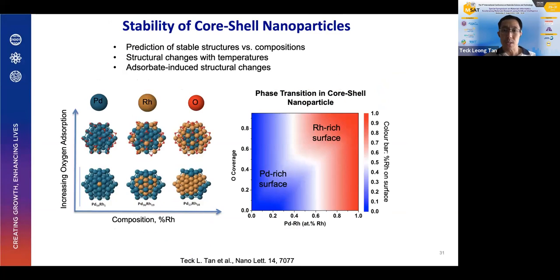This is to show that we can use similar methods to study what we call adsorbate induced phase separation. If you look at the diagram on the left, what we are trying to illustrate is that if you mix palladium and rhodium as a nanoparticle, and there is no oxygen on the surface, rhodium, which is the brown atom, likes to be in the middle. But once you include some oxygen on the surface, rhodium will prefer to come to the surface itself. This is also a phenomenon which is observed in catalysis experiments.